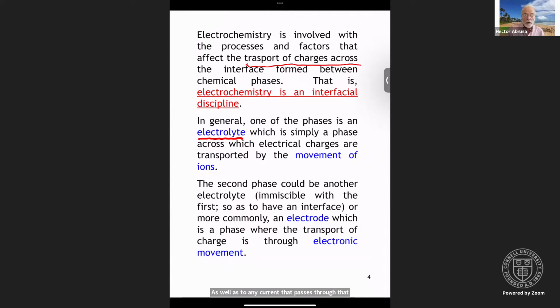The second phase could also be an electrolyte. It has to be immiscible with the first one so as to have a real interface. Or more commonly, it's an electrode, which is a phase, typically a solid, in which the charge is transported through electronic motion. And so we see the coupling of electronic motion with ionic movement, and that interaction takes place at the interface. Remember that at all times we have to maintain electrical neutrality. So if we put an electron into the interface, we have to bring a counter ion to screen that charge. There will be no free charges floating around in this context.